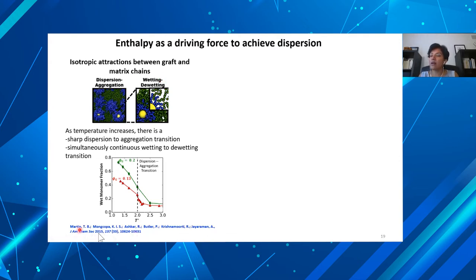Not so long ago, we had published a paper with Professor Raman and Krishnamurthy, doing experiments at Houston, that showed that if you chose different chemistries that have enthalpic attractions, right? So these chemistries are LCST-like phase behavior chemistries. At low temperatures, they love to mix, and at high temperatures, they demix. So that graft-matrix phase behavior dominates the morphology of the composites, where at low temperature, so this is reduced temperature in simulation units, but the experiments confirm this as well in that paper.